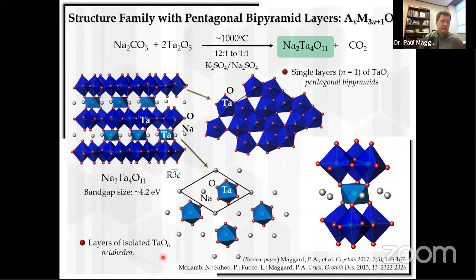Okay. So the candidate system that we looked at in the beginning was this layered phase, which has pentagonal bipyramidal layers for tantalum. And so the composition is Na2Ta4O11. Its band gap size is around 4.2 eV, and it has this trigonal space group here. Okay. And what you have are these pentagonal bipyramidal layers, and these are connected together by isolated octahedra between them. And so, for example, I've shown you one basic unit here of the connection of one layer and the next